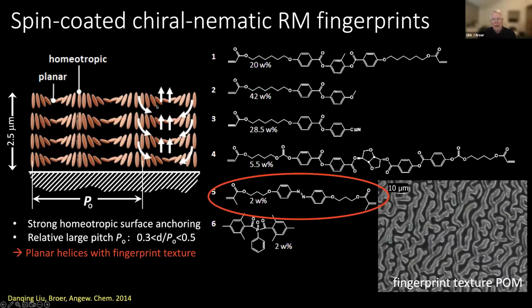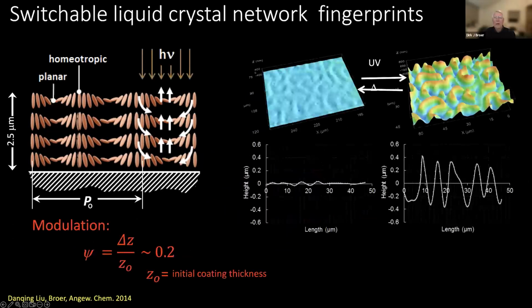So if you make a film like this, and in the polarizing microscope, it looks like this, where you have the black areas. It's the area where the molecules are perpendicular to the surface, and the bright areas is where the molecules are planar to the surface. So now we are going to excite this with UV light again, and what you will see is that it goes from close to flat state, a little bit the Marangoni effect, as you see in this case, it goes to a highly corrugated state.